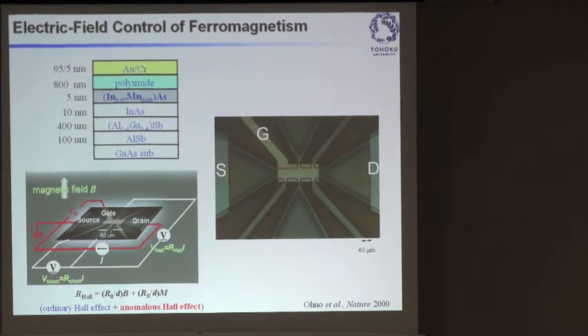So now we know that ferromagnetism in III-V ferromagnetic semiconductors is stabilized by the presence of carriers. So if we can control the number of carriers, we should be able to control the stability of the ferromagnetic phase. To prove that this is indeed the case, we have made an MIS structure, a metal insulator semiconductor structure. By applying voltage across this MIS structure, we change the hole concentration in indium manganese arsenide and probe whether we can see any change in magnetism.